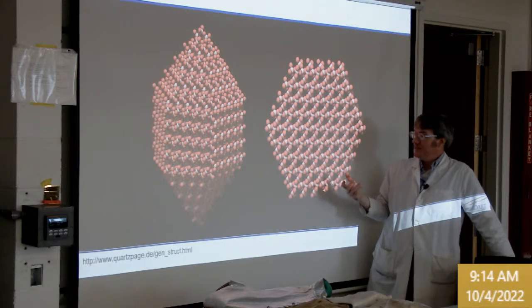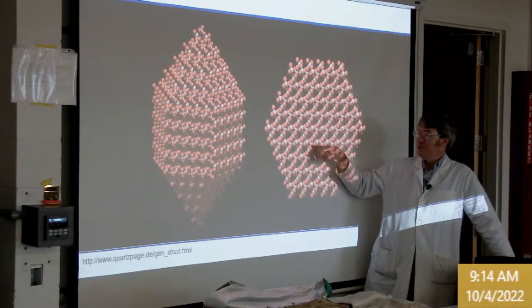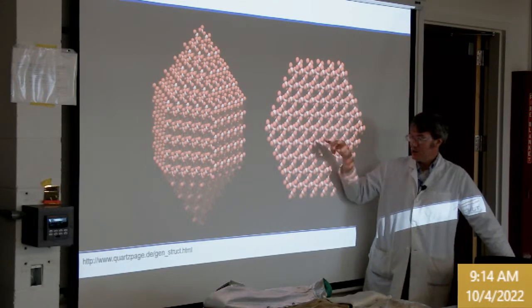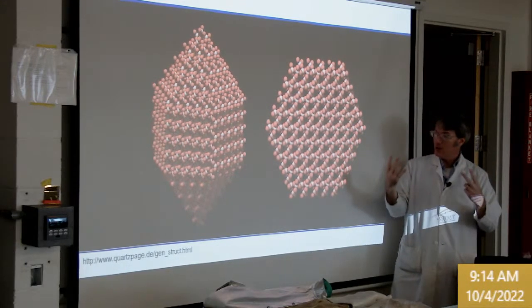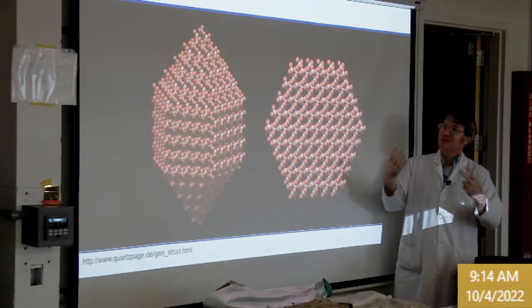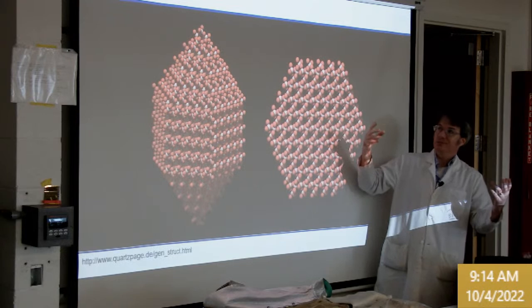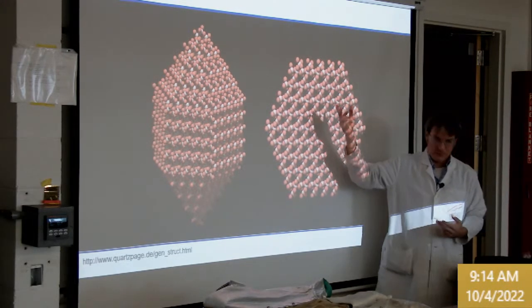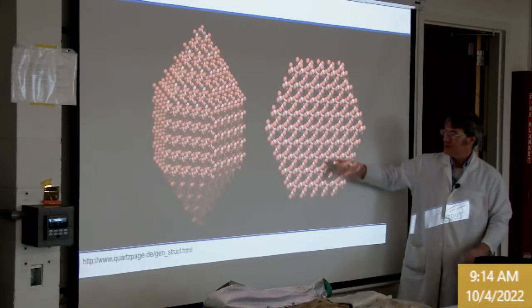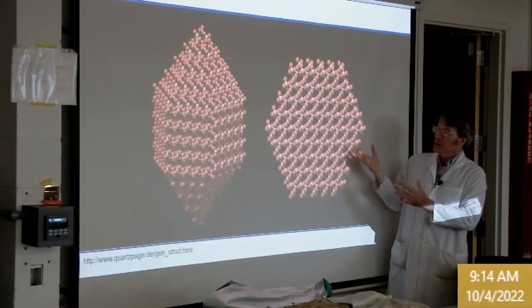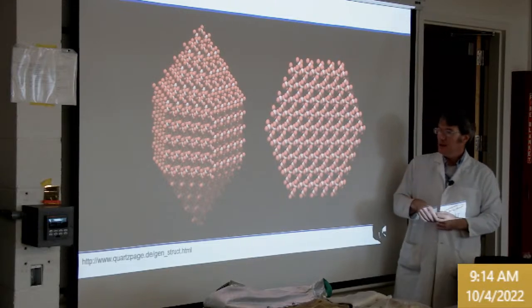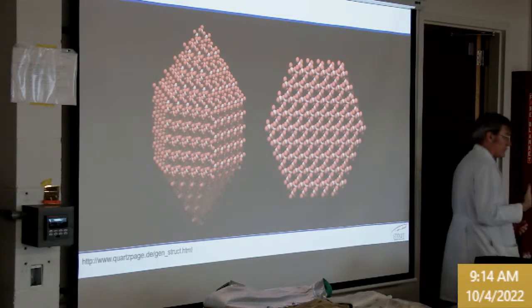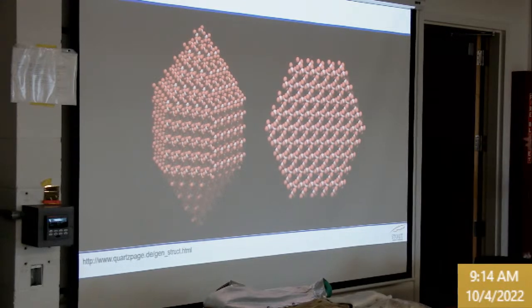The bonding motif is that every silicon is bonded to 4 oxygen, and every oxygen bridges 2 silicon. So you see that 4:2 bonding ratio simplifies, based on whole number ratios, to 1 silicon for every 2 oxygen. But you can see that just based on the bonding habit. So this is what it would look like if we could see perfectly the atoms that make up that silica crystal structure. And this would be true whether it's sand or purified silica or the Michigan lakeshore silica or Mason sand. It's all the same material.